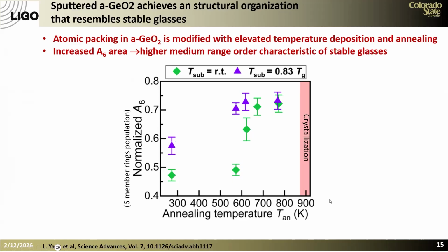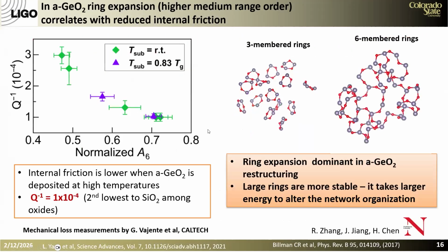In addition, annealing also alters the network organization in amorphous germania, but you can see again that the annealing is more effective whenever we start with a better organized glass. So this was the very first time that we demonstrated that this effect has been observed in an inorganic material. All of the previous studies and even the models were essentially developed for organic materials, because it's very easy to get to the glass transition temperature in an organic material.